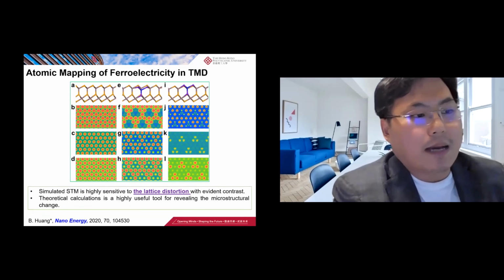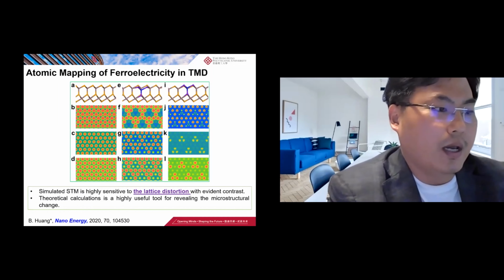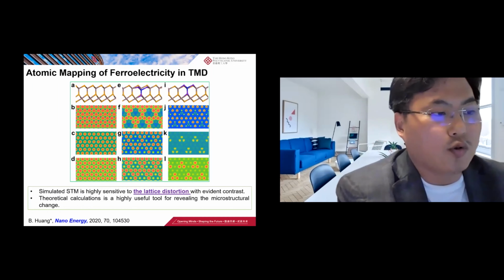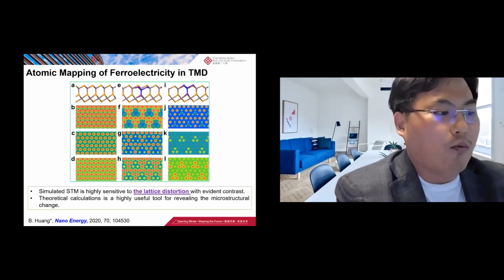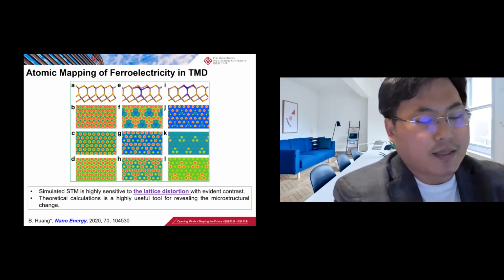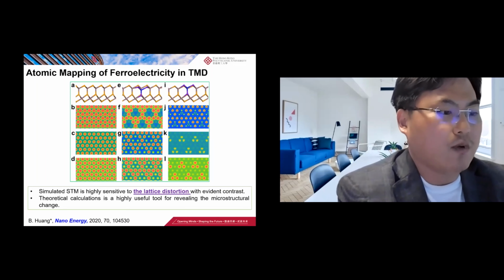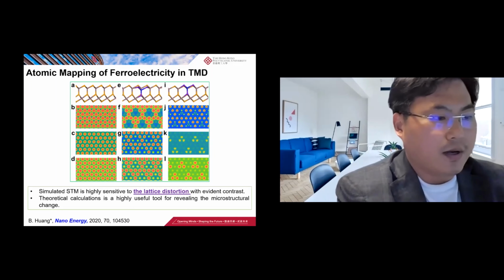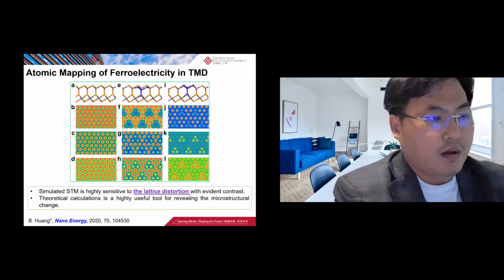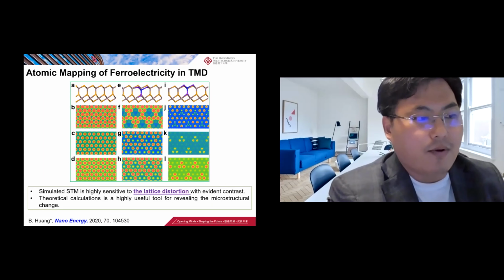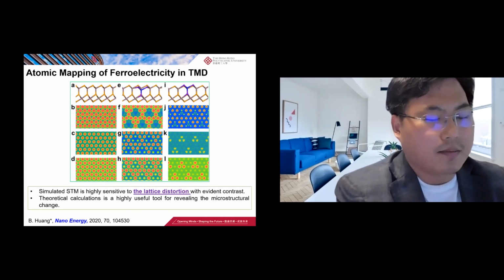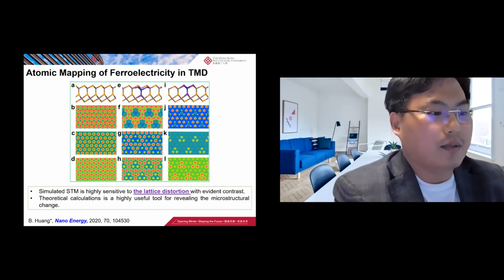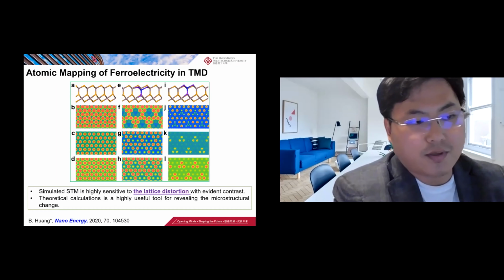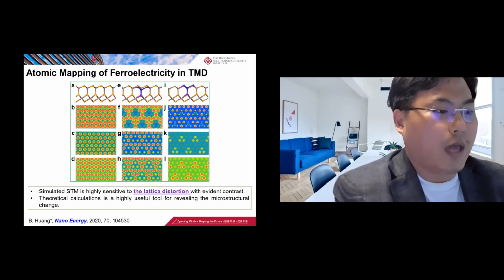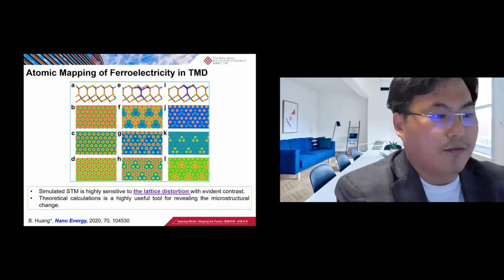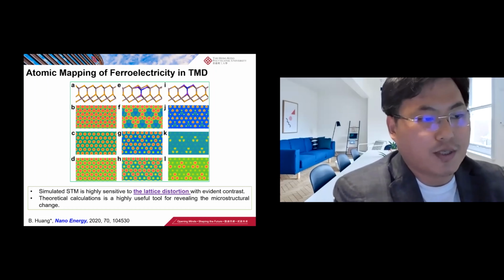So in the current two-dimensional ferroelectric materials, the scanning tunneling microscopy method is also very important. So far, it gives us atom-by-atom images at the highest resolution compared to other HRTEMs. And STM is also a very ideal tool, which can be used for atom-by-atom modulation in these atomic-scale applications. So we also carried out simulated STM on different indium selenide structures with different intrinsic defects.